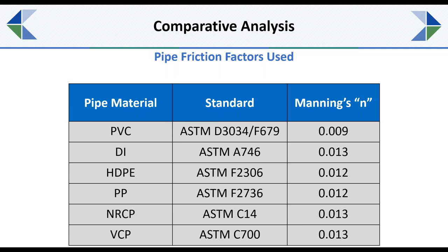In this case, for gravity flow, we're typically looking at Manning's coefficients. So the lower the value, the smoother the surface is. So PVC pipe does have that lower factor with it. HDPE does not, mainly because of the interior bead that happens during the fusion process, it does affect their flow coefficient somewhat. And they're also a smaller diameter, which does affect their flow coefficient as well. And then ductile iron pipe is also listed there. NRCP is non-reinforced concrete pipe. And VCP is vitrified clay pipe, so clay pipe. Those last two materials are utilized, not quite as much.